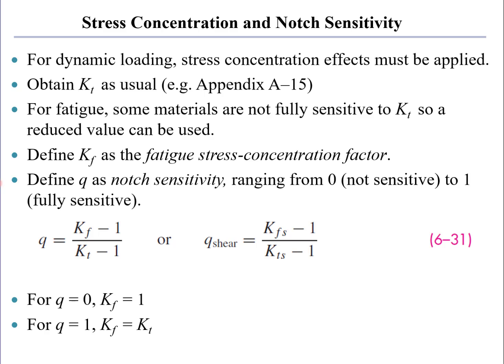expected fatigue lifetimes. So you may recall that in the Marin factors, we had a geometric size correction factor that had to do with the diameter of a rotating circular shaft or changes in effective diameter for non-rotating shafts. Those were purely a volume effect on the initiation of a fatigue crack under high cycle fatigue loading. The same thing is true of stress concentrators. In regions of high stress, the volume is somewhat small, and so we adjust the stress concentration factor to account for a volumetric effect that would influence the fatigue lifetime.